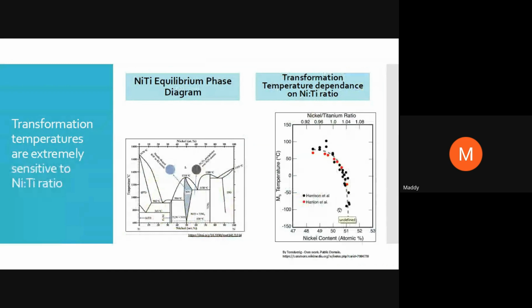Okay, so I was mentioning that it's a challenge to melt nitinol. Why? Let's look at the phase diagram. So if you see here, the nickel and titanium phase diagram, you can see here that roughly at 50-50 atomic percent, you can see how narrow the NiTi phase field is, right? So maintaining a composition control is extremely difficult.